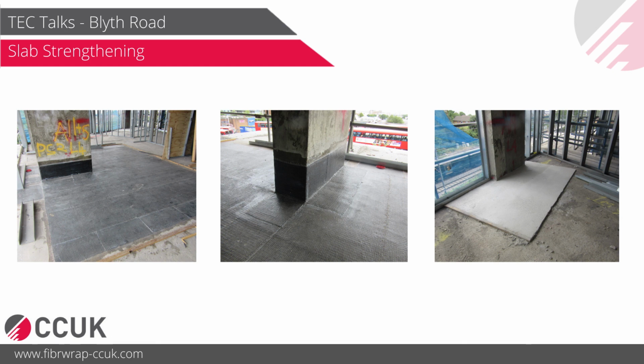In this instance, we used the cementitious fire protection system, which was tested for up to a 4 hour fire rating. So there are tested and approved systems available in the industry. If needed, carbon fiber can be fire protected. That's great.